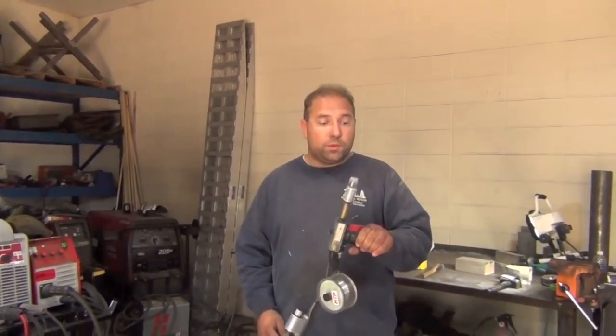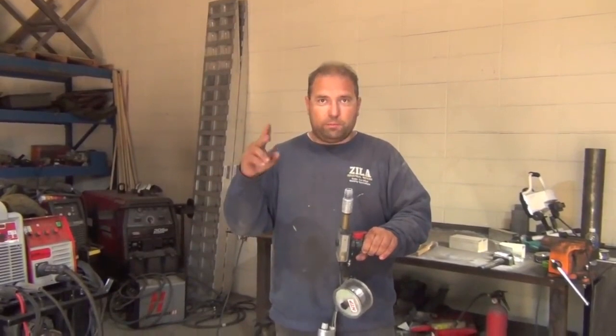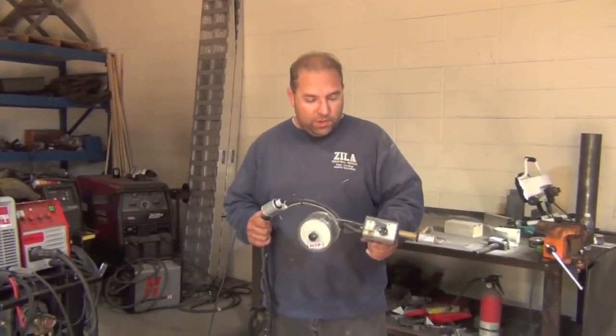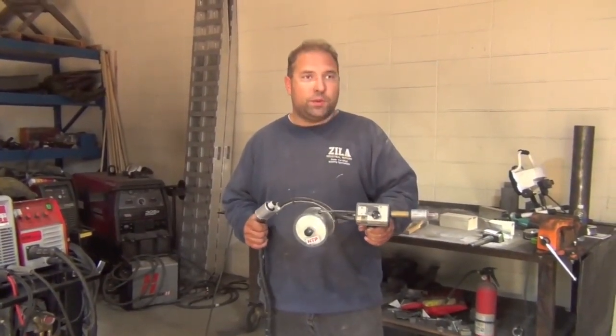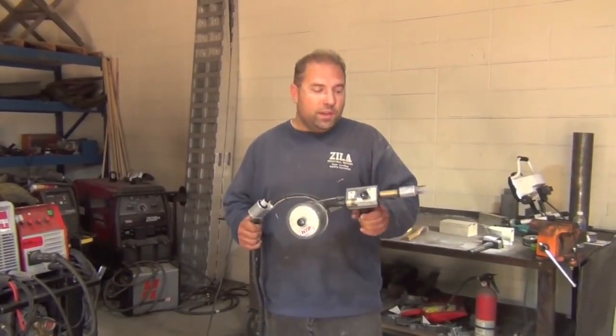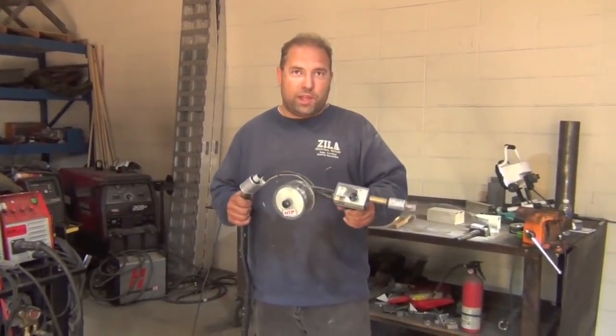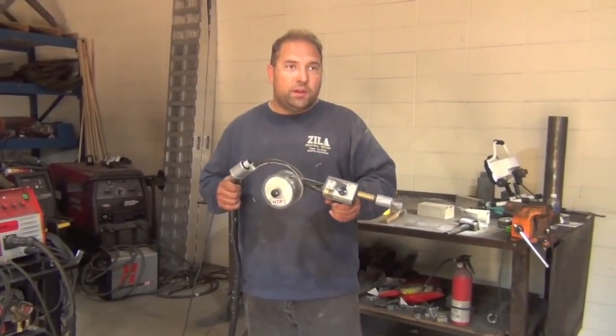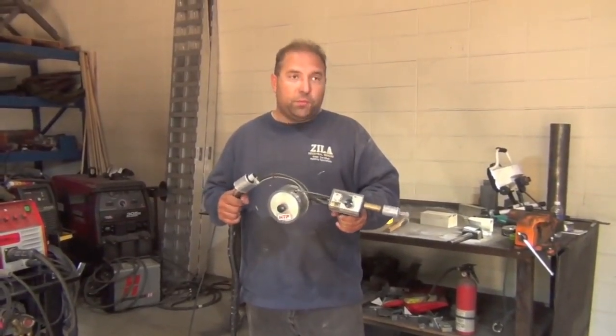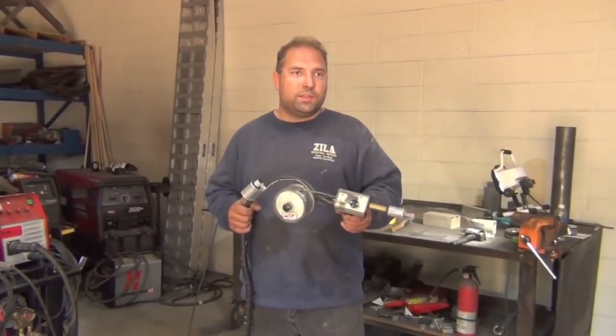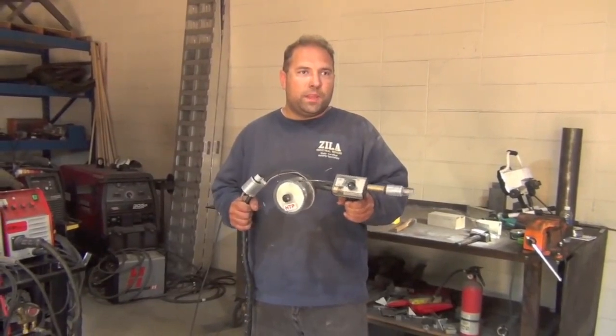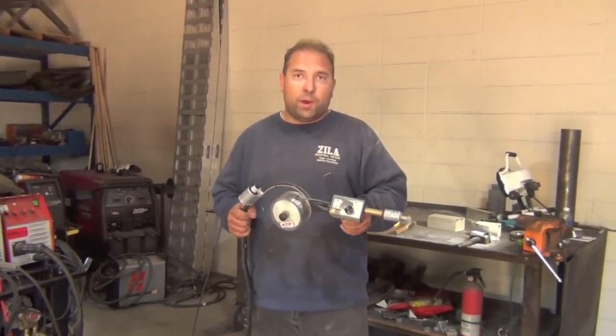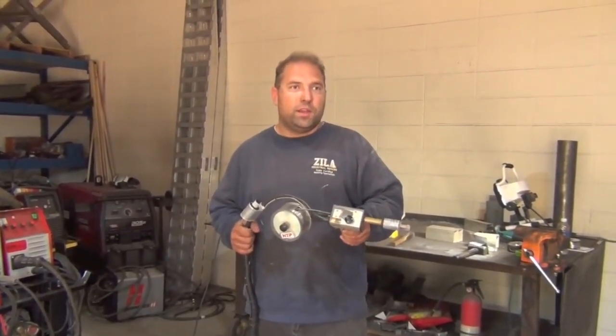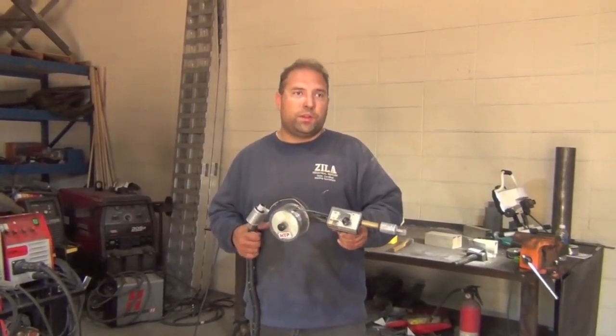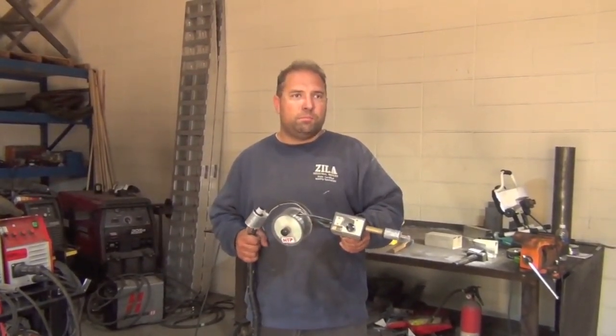As far as welding, it welds just like regular MIG. You weld in spray transfer, and it's pretty easy to learn. It's a high metal deposition rate, so that means you move fast. There's a lot of wire coming out, a lot of linear footage of weld that you cover in shorter time than TIG, and it even works, limited, outdoors if the wind is not blowing too hard, if you work on dump trucks or trailers, and that's about it.